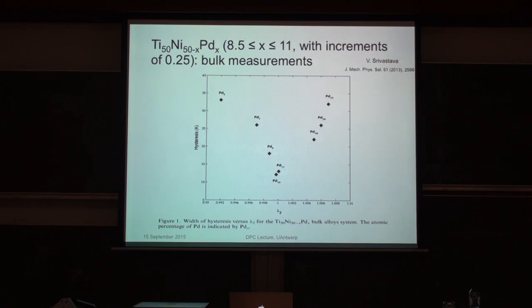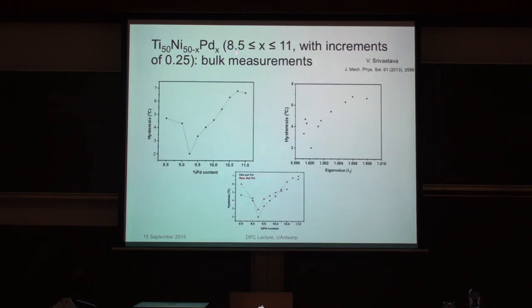The point is that graph is very, very sharp. So here's an example. Here's a bunch of alloys with different amounts of palladium, and each one's hysteresis is plotted versus lambda 2. And there's the old alloy we used to think was the lowest, PD11. And now you go in this box, and you start doing compositional changes where you change the amount of palladium by 0.25% increments, and you find that, wow, you can go down to, in fact, 2 degrees in a bulk material. And so with very careful compositional changes, it does actually matter. And typically in bulk material, we can get 1 and 2 degrees if we do those very, very precise compositional changes. So that's why it was missed previously.